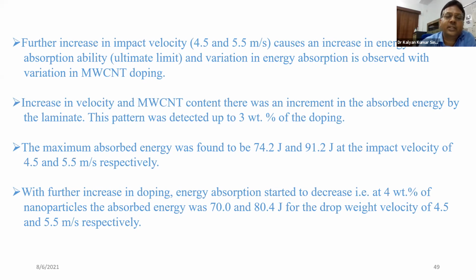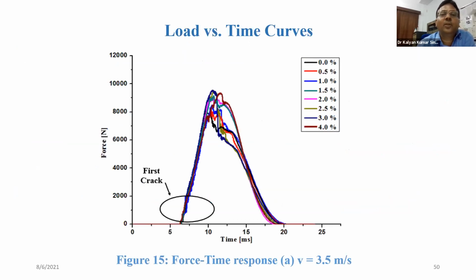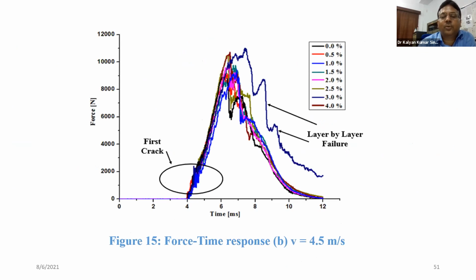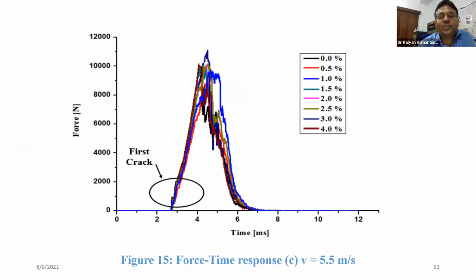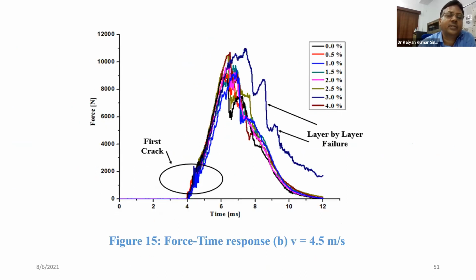Now, with the further increase in the doping, energy absorption started to decrease. At 4 weight percentage of the nanoparticles, the absorbed energy was 70 and 80.4 joule for the drop weight velocities of 4.5 and 5.5 meter per second respectively. See the load versus time curve, how it is showing from the 0 weight percentage, without any MWCNT mixing, up to the 4 weight percentage. Now look at the force time displacement graph when the velocity is 4.5 meter per second. See the different types. See the 5.5, what is going to happen? 4.5, 5.5, 3.5, these three I am showing you. The first crack, if you look at this figure, see the first crack here, see the first crack here.